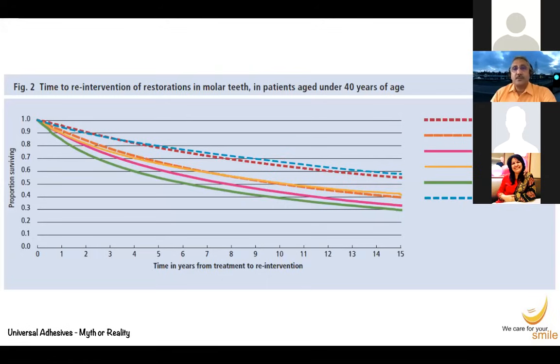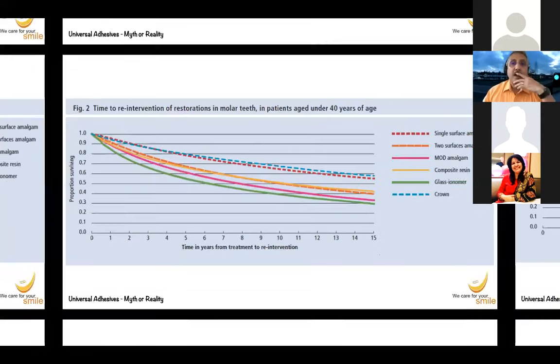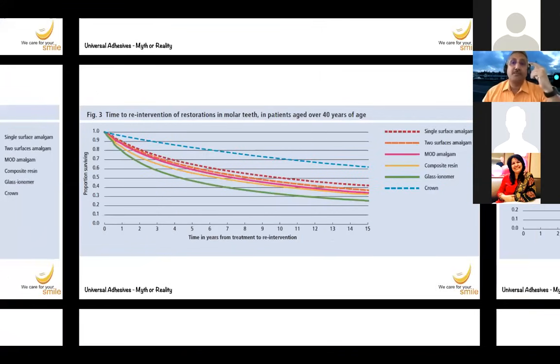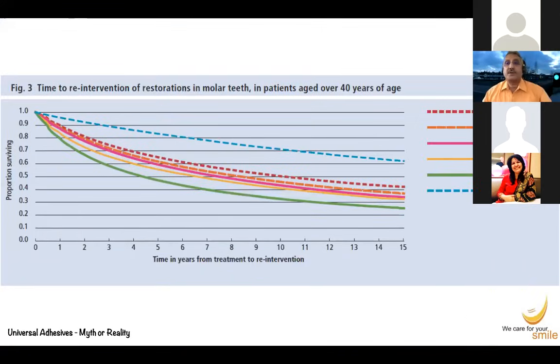But what's more important is, if you start off from the timeline 0 and you go up to 15 years, you see nearly 30 to 50% of restorations would need to be changed or repaired within 10 to 15 years. Now, this is a good figure. In India, this figure is in the low 5 to 10 years, according to me. Now, that was for patients below 40 years of age. What happens with patients over 40 years of age?